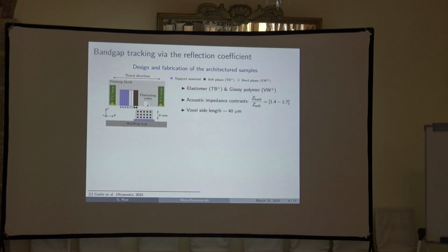So why do we play with this kind of configuration? Because this is why we started the collaboration with Liège, because you can print this kind of material using a polyjet 3D printer, which is able to print almost like an inkjet printer on paper, multiple materials and gradients and also combination of them, but we will use two materials, an elastomer, which is called Tango Black, which will be black and is very, very soft. It's really an elastomer in static properties. When you put waves inside, it's much more rigid. And a glassy polymer, which is called Vero White, which is much more stiffer.